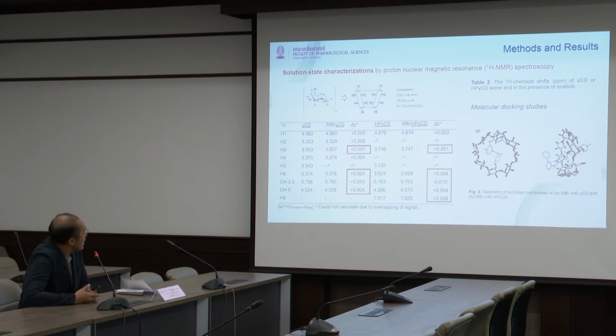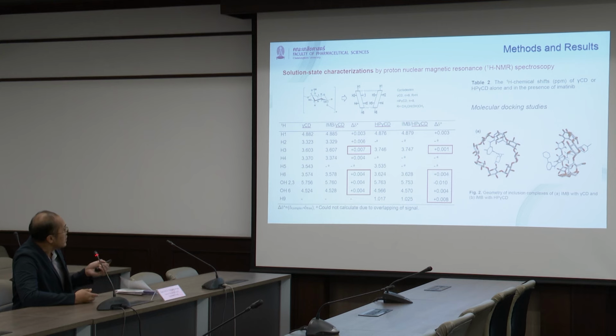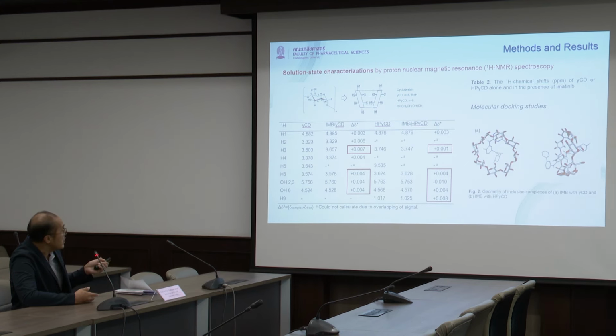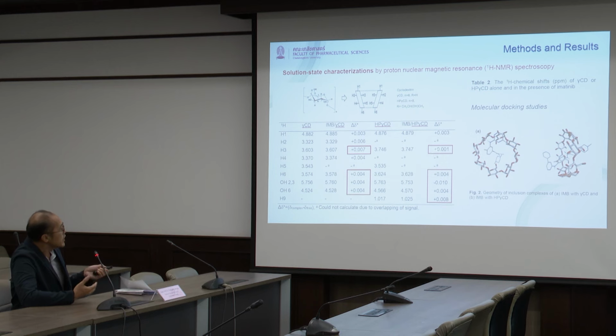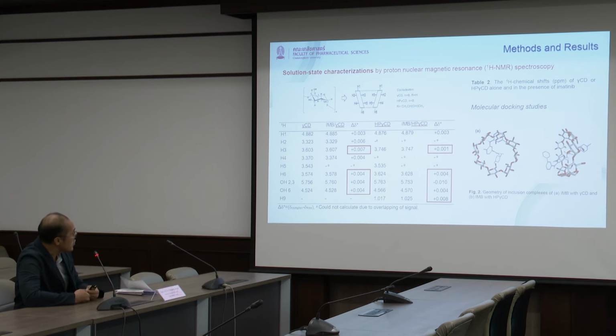Then we confirmed the solution state characterization by using proton NMR. Normally, when we study the inclusion complex, H3 and H5 should show a chemical shift when the drug is included in the cyclodextrin cavity. The H3 shows a higher chemical shift of the protons. And the outer protons of the cyclodextrin also change chemical shift, enhancing the stabilization. This is the molecular docking that confirms the solution state by proton NMR, that the drug can go inside the cavity of the cyclodextrin.